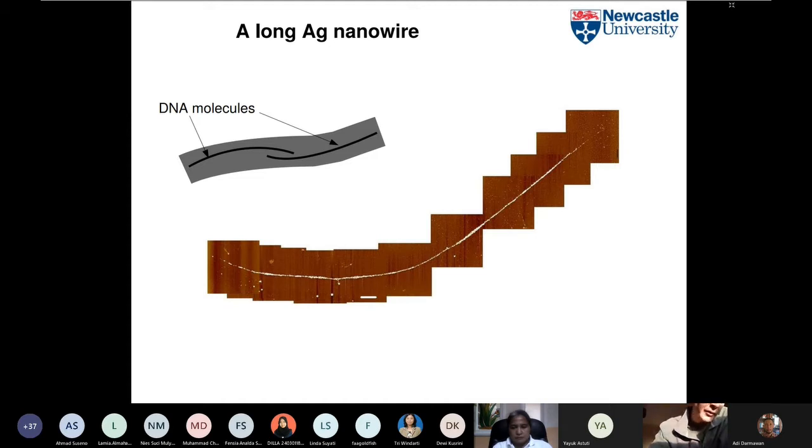And this nanowire, which was prepared from lambda DNA, is actually about 150 micrometers long. What he did was he collected a number of AFM images and moved along the wire and managed to collect a picture of the whole wire. So this is not a common occurrence, but I just wanted to say that we don't necessarily make things that are exactly the length of the template, because it's possible that the material that we coat the template with can act to join up several different molecules. So this example here is certainly many molecules long.